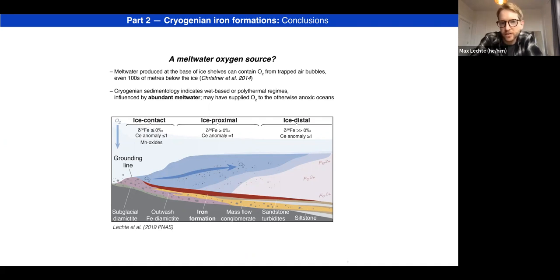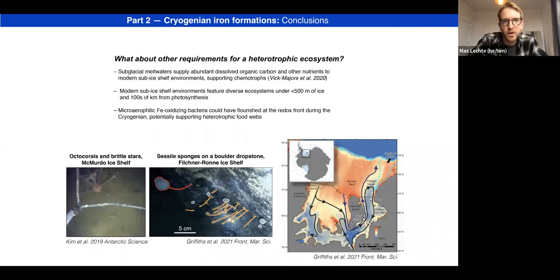The sedimentology of the Cryogenian glacial deposits indicates that they were likely wet-based or polythermal regimes and therefore were influenced by abundant meltwater. And we suggest that potentially this is an oxygen source to the synglacial oceans that has not really been fully explored in terms of its significance. I kind of pushed this idea a little bit further and got a bit arm-wavy in terms of what the significance might have been for ecosystems in the oceans during this time.